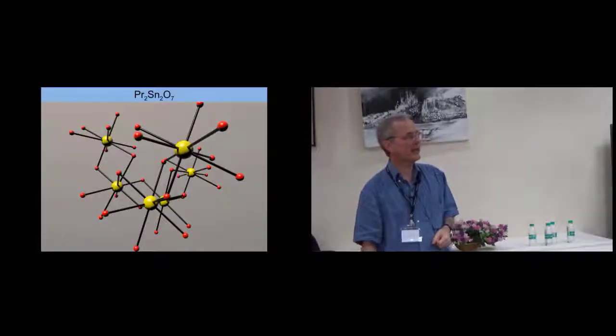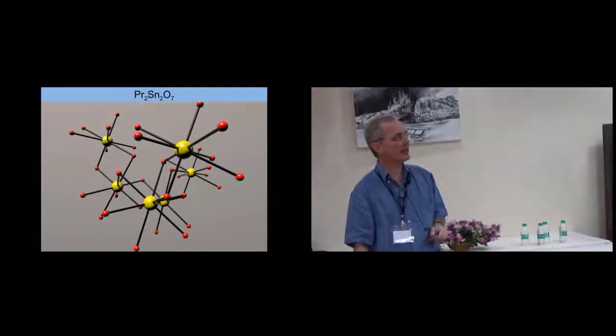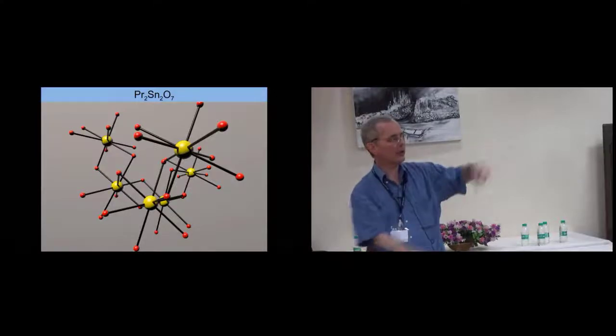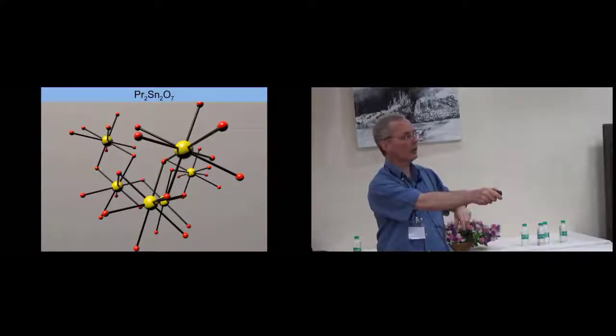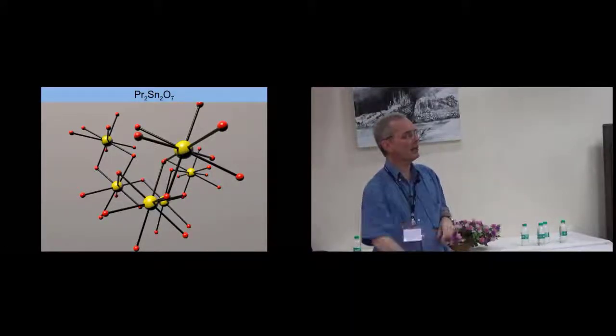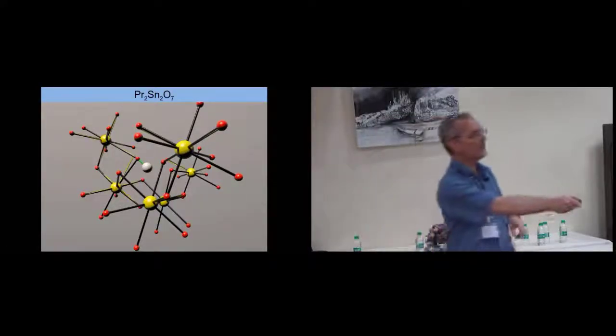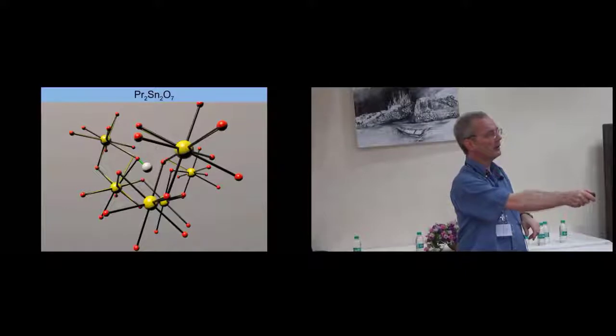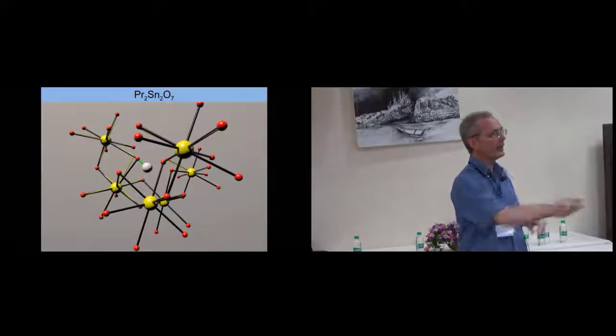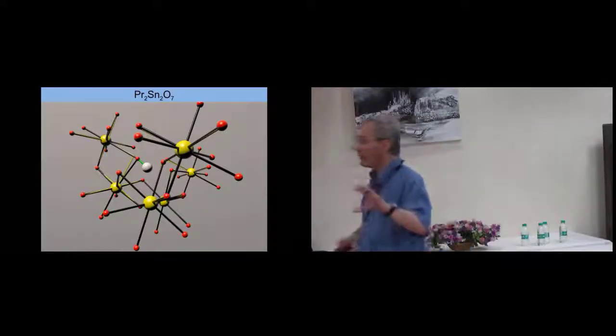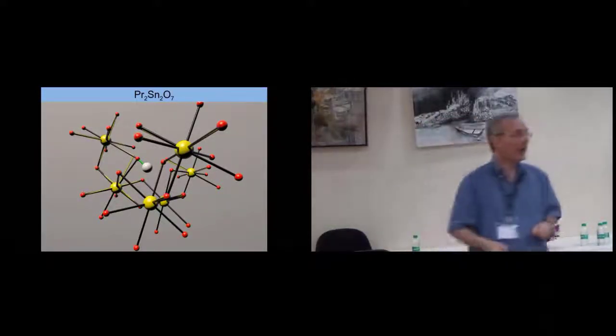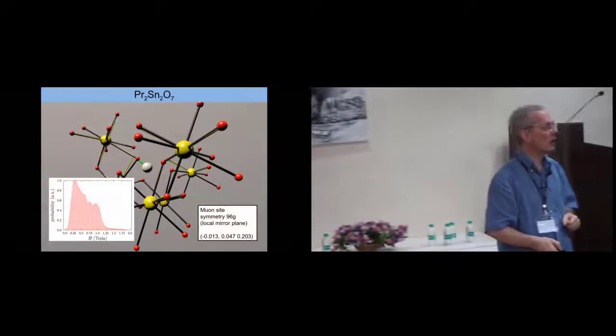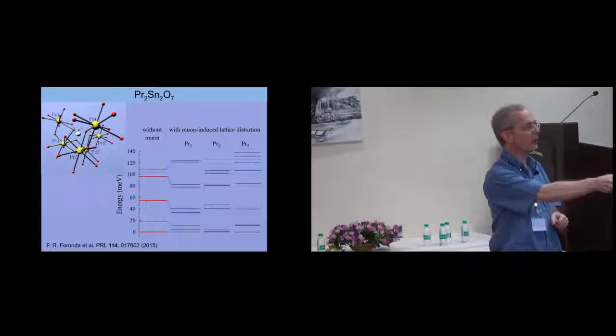Now another way of representing this is the picture I showed right at the beginning. So here, I've got rid of the tin. There is praseodymium, oxygen, and now I put the muon in. And you see what happens, this bond bends and this bond lengthens. But in fact, the environment around these two ions is then completely changed. And this affects the crystal field. And we know this because we can do crystal field calculations.